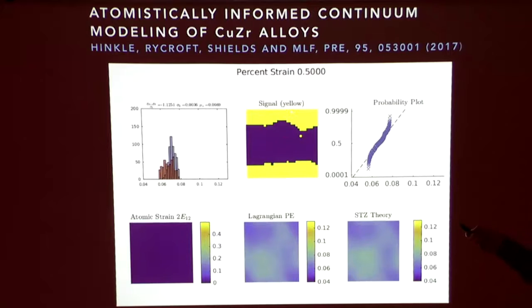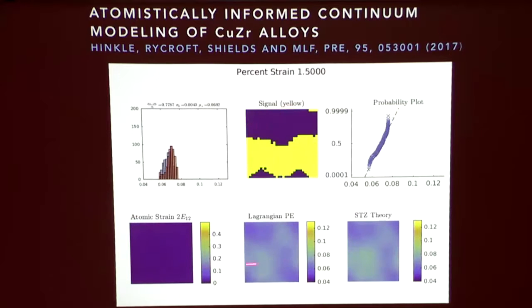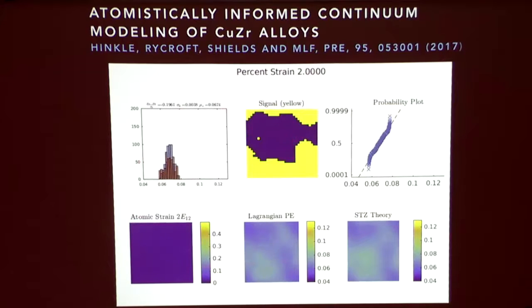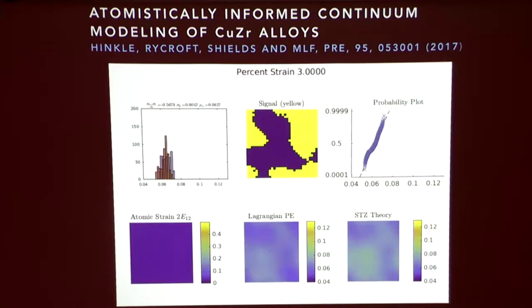And it's all basically deforming elastically. It's pretty uniform. And then eventually, you'll see it'll localize in the center. This shows the histogram of the potential energy for the material inside and outside the shear band, in the blue region and the yellow region. And then this shows the strain in the system, the potential energy in the system, and this is the simulation with Chris's code. So this data, all this data is from molecular dynamics, and this is a continuum simulation.